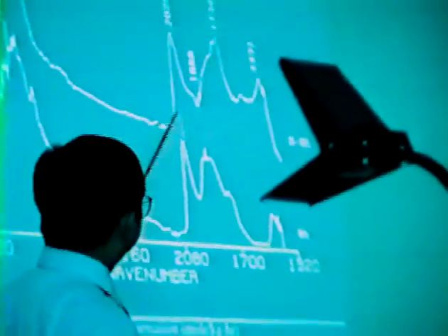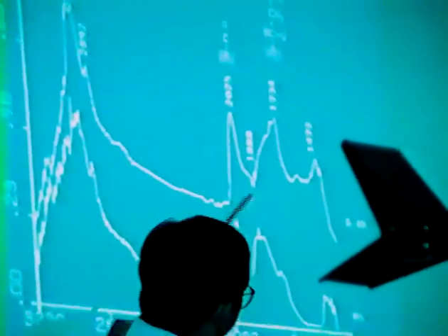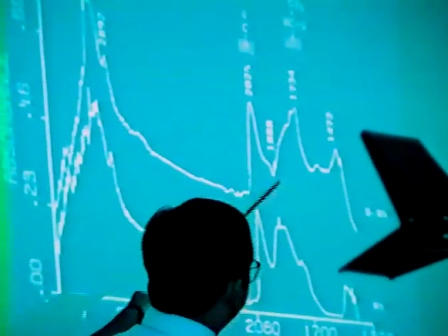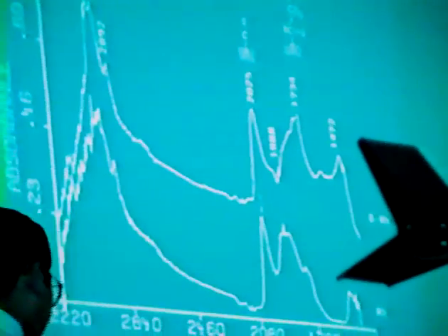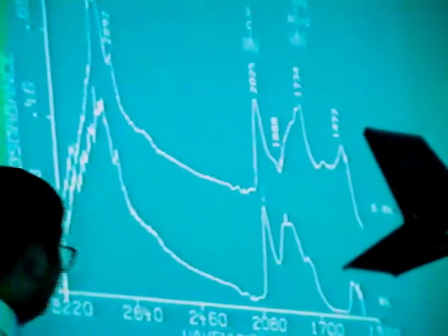We see the bridge CO here again was suppressed, so you can see there's a clear ethylene band here, and additional sulfur increased the rate of formation of propionaldehyde and suppressed the formation of ethane. So this result confirms the linear CO is a species involved in the CO insertion.